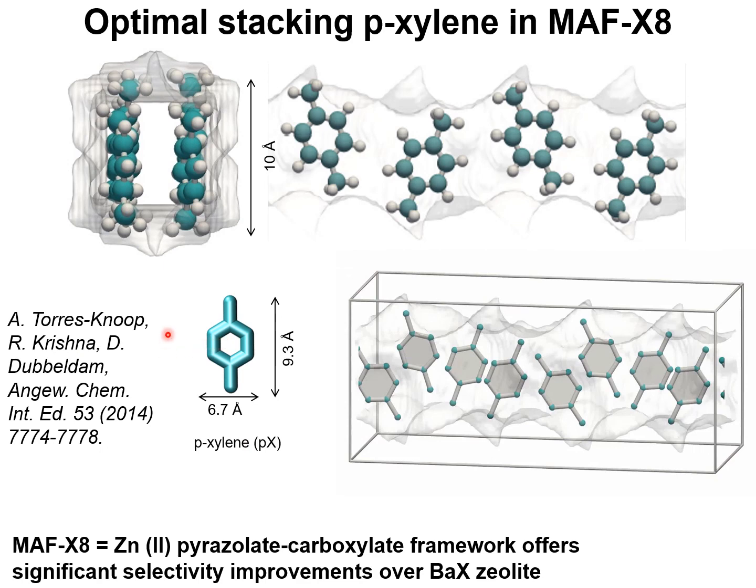For optimal stacking of paraxylene within an adsorbent, we need channel dimensions which are about 10 angstrom so that paraxylenes can stack vertically.